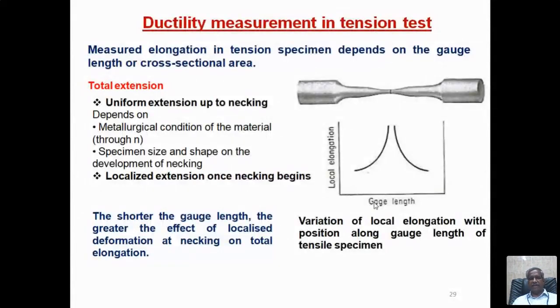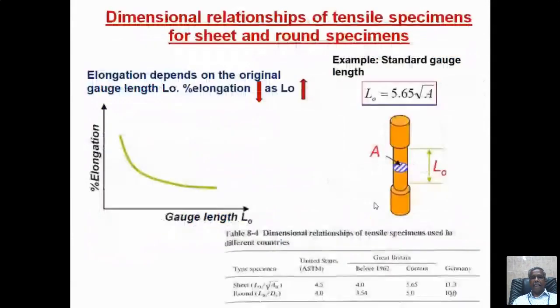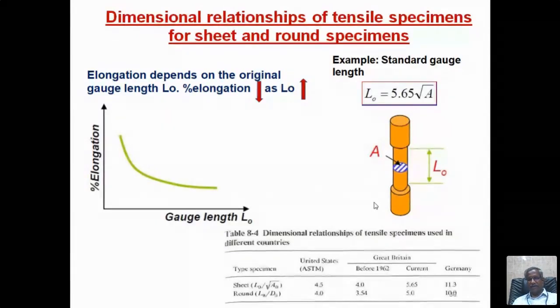And ductility measurement, as you all know, is elongation, and you have to measure the gauge length. And it is dimensional gauge length again, right? The standard gauge length, as per the standard, is 5.65 square root of A. Here they have given the ASTM standards and the other things, for the sheet specimen and the round specimen. If you know the area, you can fix the gauge length with respect to the area. Gauge length should be fixed based on the diameter or the area of the specimen, okay?